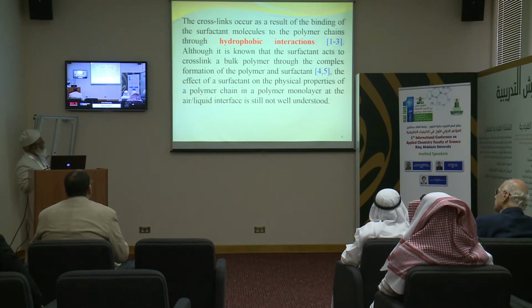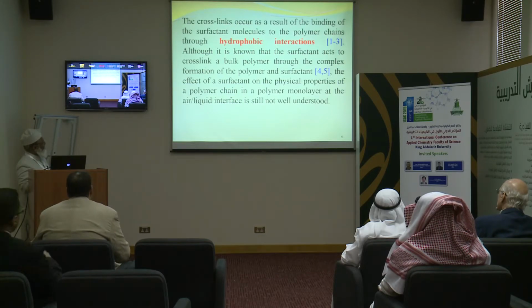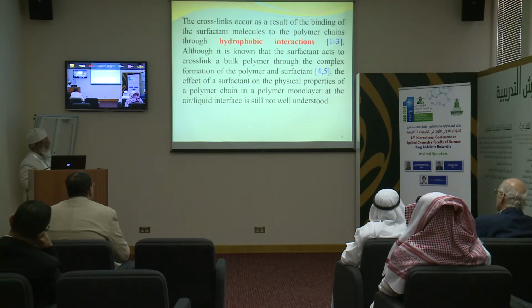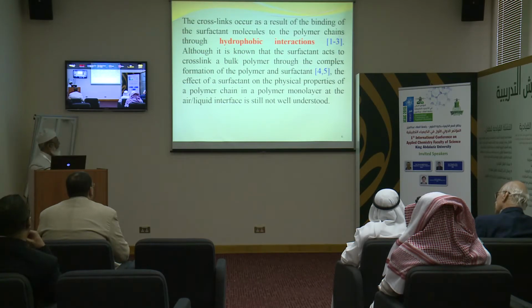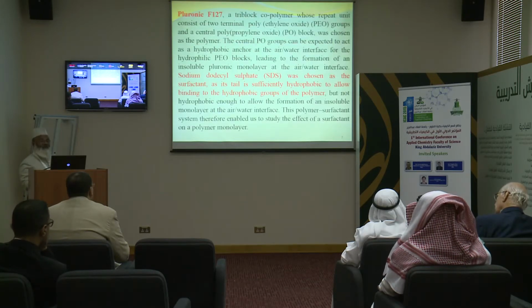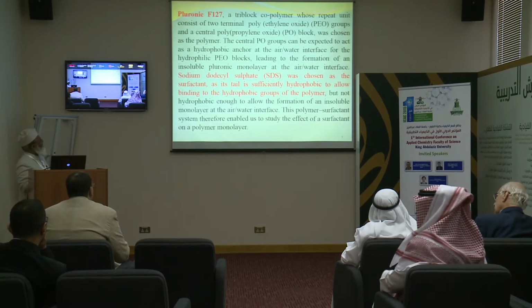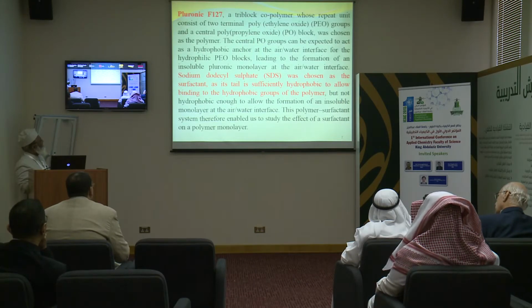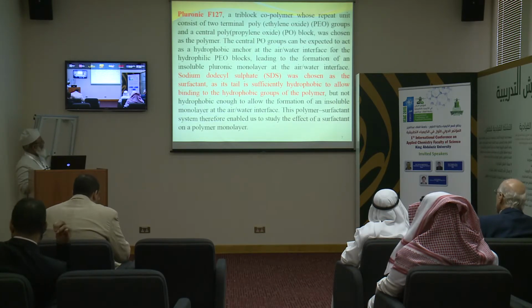The cross-linking basically occurs because of hydrophobic interactions, and it is known that the surfactant acts to cross-link a bulk polymer through the complex formation of the polymer and the surfactant. The effect of the surfactant on the physical properties of a polymer chain in a polymer monolayer at the air-liquid interface is still not very well understood. Pluronic, which is a triblock copolymer whose repeat unit consists of two terminal polyethylene oxide (EO) blocks and a central propylene oxide (PO) block, was chosen as the polymer.